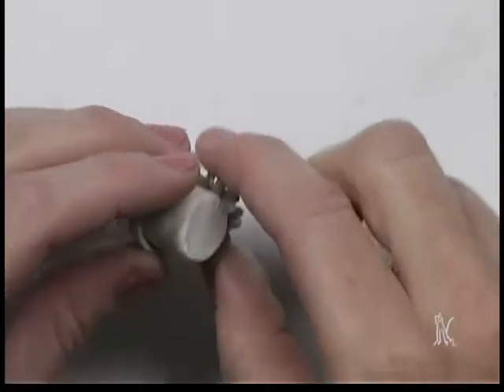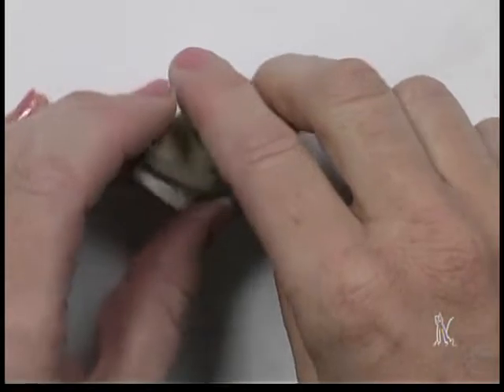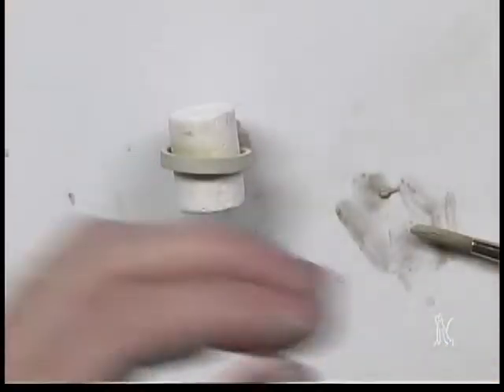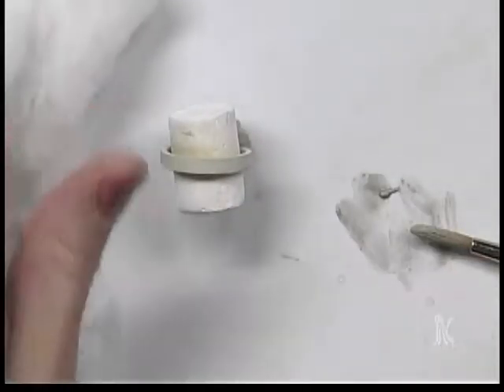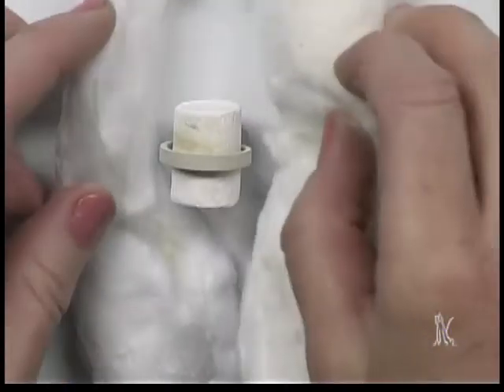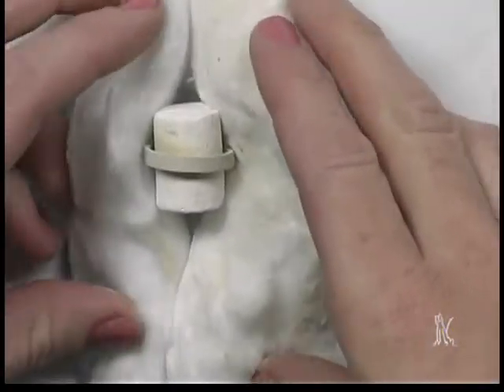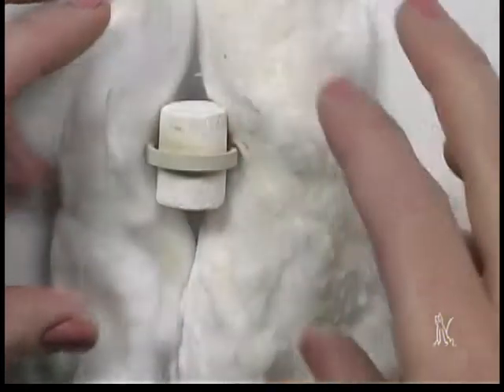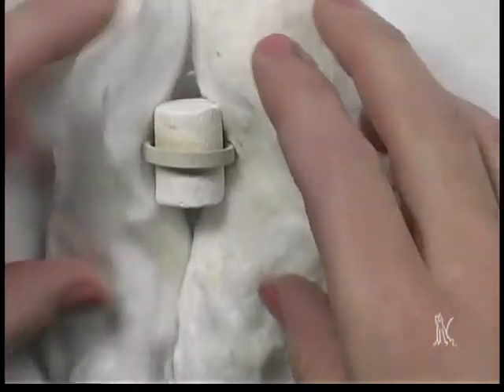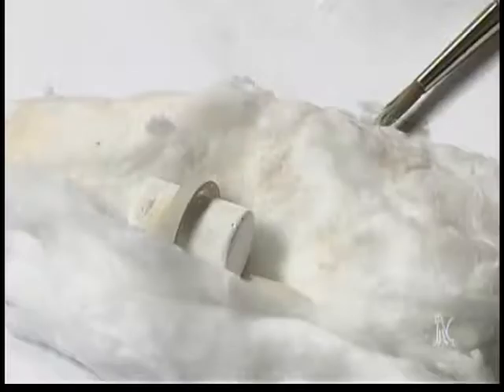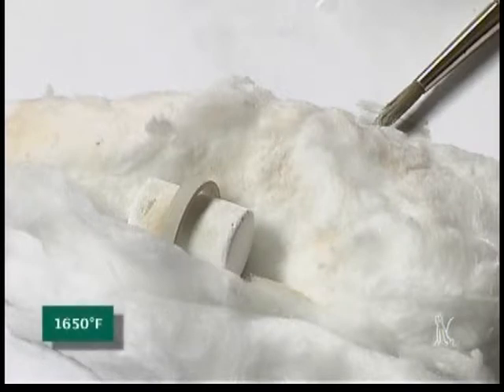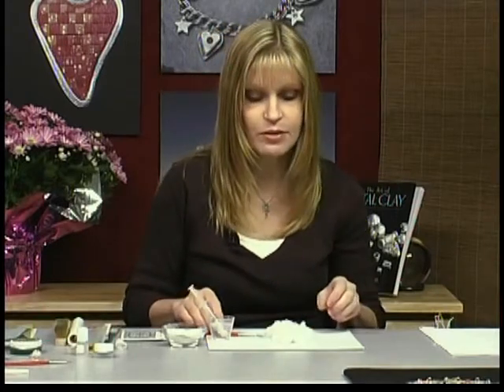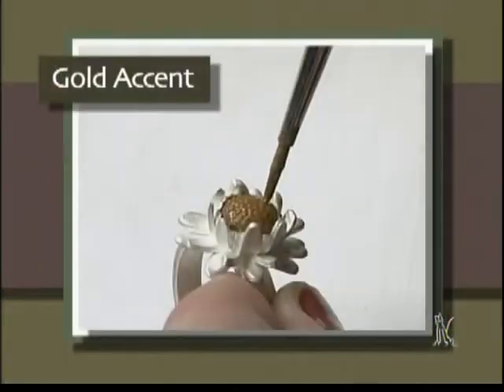So I'll turn this ring over when I'm ready to fire it and insert the ring form. And then on your kiln shelf, use a little bit of fiber blanket on each side to support it, to make sure that it doesn't go anywhere or roll off when you're firing it, and fire it just like that in the kiln. This could be fired at 1650 degrees Fahrenheit for any of the recommended times, anywhere from 10 minutes to 2 hours for maximum strength.